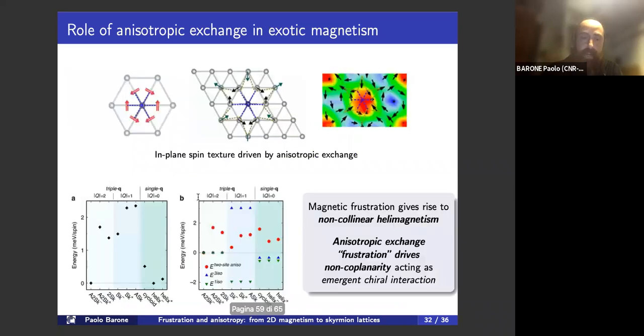And now we can compare the direction of this principal axis for the exchange anisotropy with the in-plane spin texture of the spins. And you see that there is a one-to-one correspondence. So basically we can think of this triple Q state as a superposition of a spiral, which is actually stabilized by the presence of this anisotropic exchange, which as a plus also provides a well-defined in-plane texture of the spins.